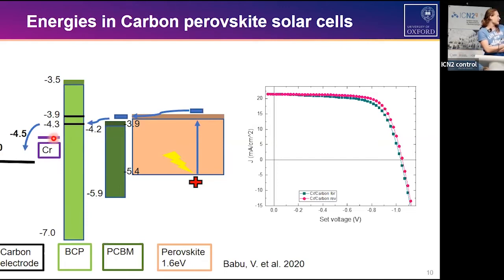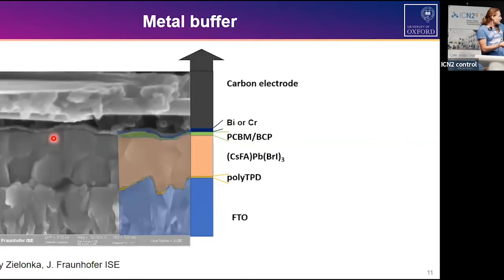It did work. After a lot of optimization, we obtained really good results with it, efficiency-wise. I was really happy. We beat their efficiency in their paper by more than 10%. But I also tested something new, multiple different metal nano layers in between. We had promising performance, and all our devices had a few nanometers of evaporated metal that seemed to protect our devices pretty well.